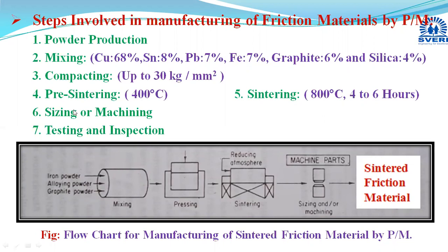And after doing the sizing or this machining, that component is given to the testing and inspection. Okay, this is the final component obtained, and this friction material is termed as sintered friction material, because we have done the sintering process on it. Now it will give you the desired strength also. After sintering, desired strength and hardness will be given in that material, with sufficient coefficient of friction.